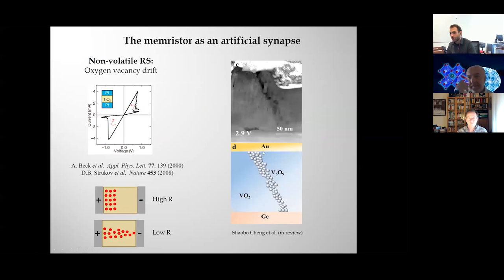Here. So in reality, what's happening is that the V2O3 itself is also a correlated oxide, and it also has an insulator to metal transition. So when you actually create these filaments, you see two transitions. One is the bulk VO2 that is undergoing the transition, and then at lower temperature, you see the V2O3. So yes, what you comment would be possible. You could find a temperature range in which the V2O3 would be.